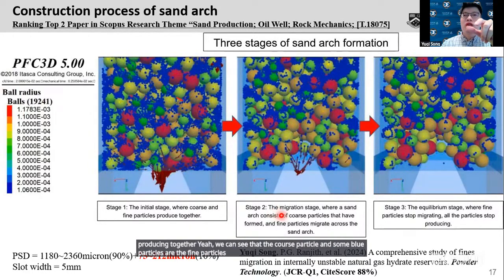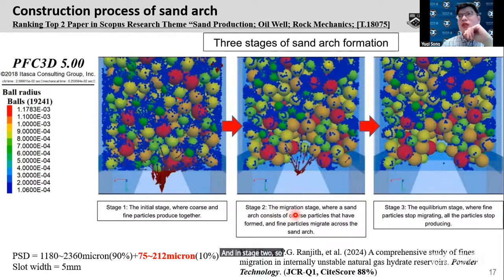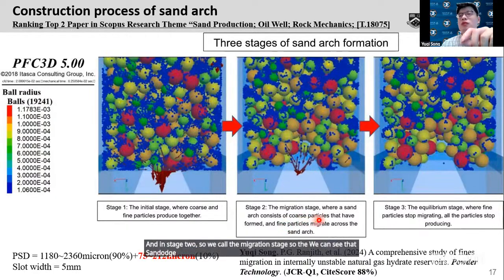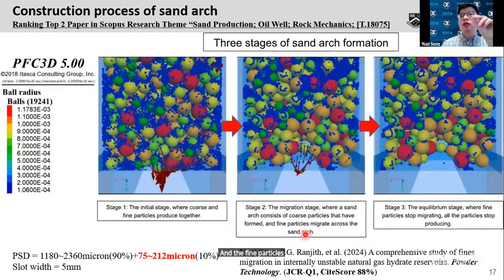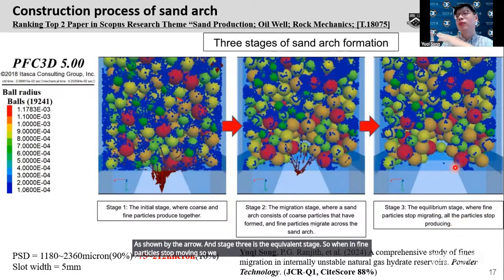In stage 2, we call it the migration stage. We can see that a sand arch consisting of coarse particles has been formed, and the fine particles are still migrating across the sand arch. The coarse particles nearly stopped moving in this stage, but the fine particles are still moving, as shown by the arrow. Stage 3 is the equilibrium stage. When the fine particles stop moving, we know that the sand production has stopped and is controlled.